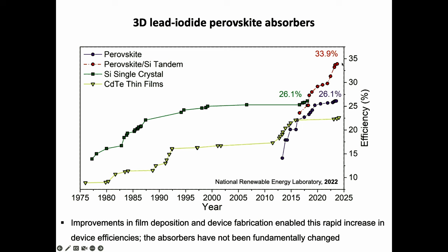So let me tell you what this graph does not tell you, though. It does not tell you what happens to the efficiencies when we actually build a solar cell that's large enough to go on your roof. These are all lab-sized chips, and you can reach these very high efficiencies on a smaller chip. But these efficiencies plummet when you actually consider a large-scale module. And this does not tell you anything about stability, which is really the key problem here. These materials are extremely unstable.